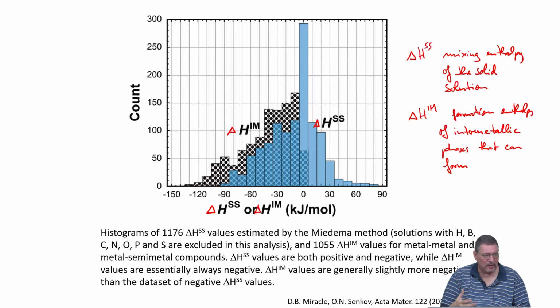This is something you can only infer when you have done diffusion measurements, or when you do very complex, long time annealing treatments, but then you never know when to stop, right? So the real correct time to pick for these experiments is very difficult to estimate ahead of time based on data, unless you have diffusion data. So it means you could have waited for 3 months, which is a long time already when you do a PhD thesis, but maybe it should have been 6 months. You will never know if you don't try, or if you don't calculate the rate, the kinetics from diffusion data.